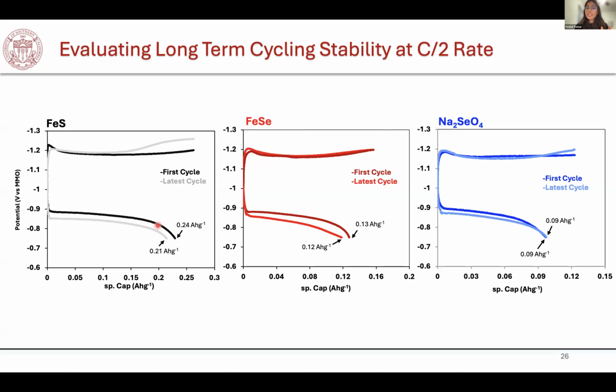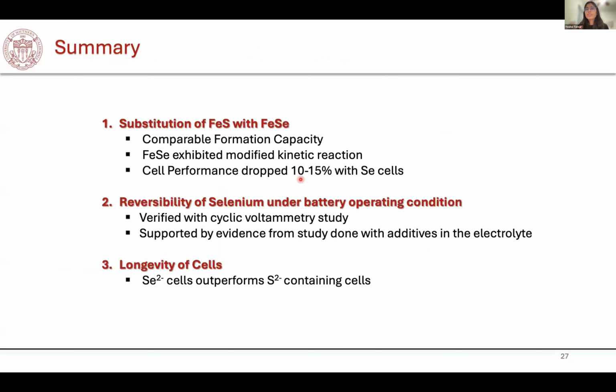not significantly changed. And you have to understand that when I say 2000 cycles, it equals around 8,000 hours of continuous cycles of charge and discharge, which equals around 1 year of running of these cells. And these cells were able to maintain their polarization curves after going through so many changes. And this tells how robust these electrodes are, and so they can serve as a great potential for large-scale energy storage devices.